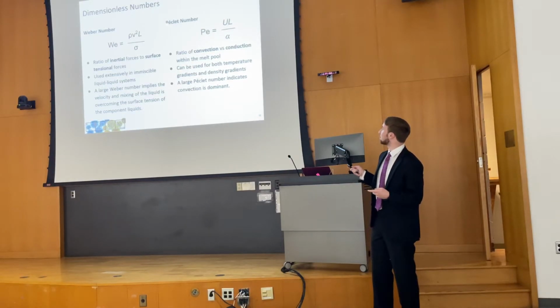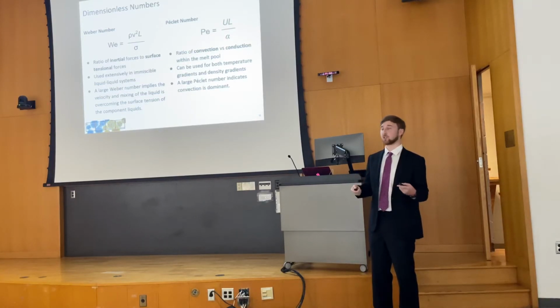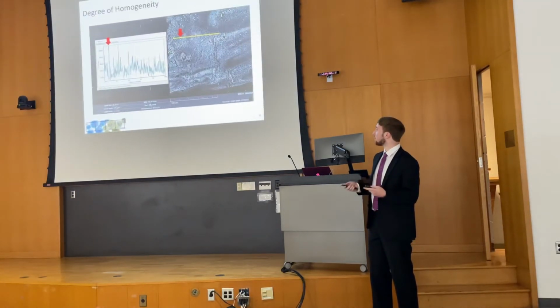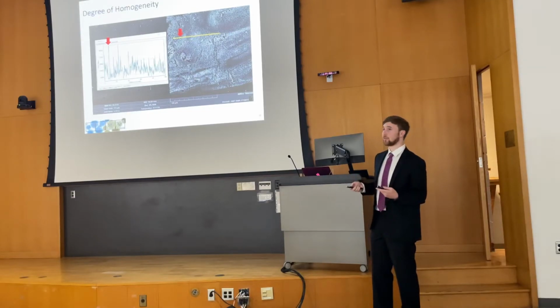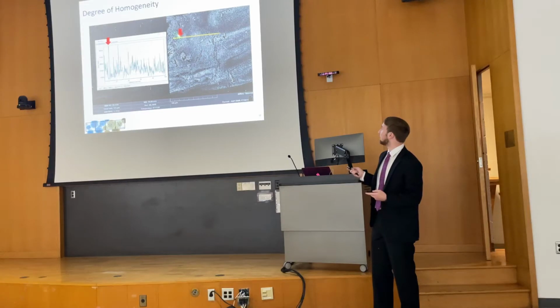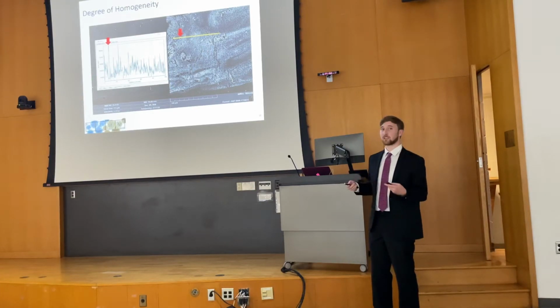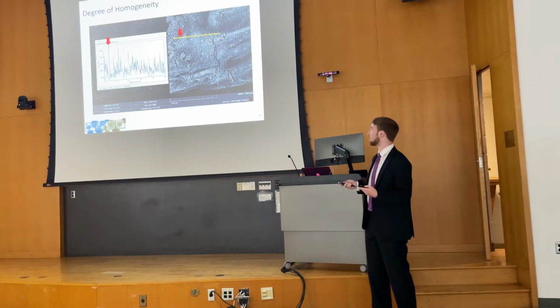The Peclet number is a ratio of convection to conduction, and a large Peclet number indicates that convection is more dominant. We wanted to compare those values to a degree of homogeneity. So we had these SEM scans from scanning electron microscopy, and we drew lines across various points and then created these line charts of grayscale values versus distance across. And then I used two methods to try and quantify homogeneity from this data.